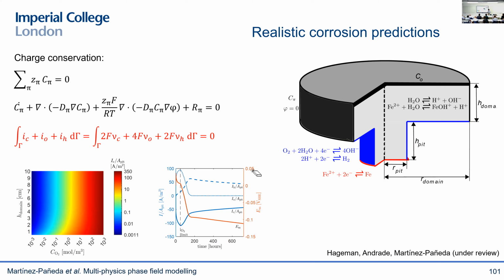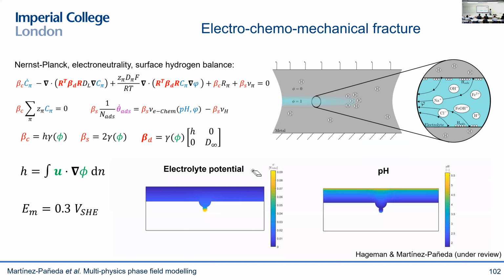And then we can see, by the way, this is work with Carmen Andrade, who is now also affiliated to CIMNE, what the balance is between the cathodic and anodic reactions. We can see, for example, how the corrosion current density depends on the concentration of oxygen, how as we run out of oxygen, the corrosion reaction can maintain itself through this charge conservation with the cathodic reaction. So we can learn things about the physics of the problem, and we can simulate what I think are real conditions, which is something that one cannot do in the lab unless you want to wait for 50 years.